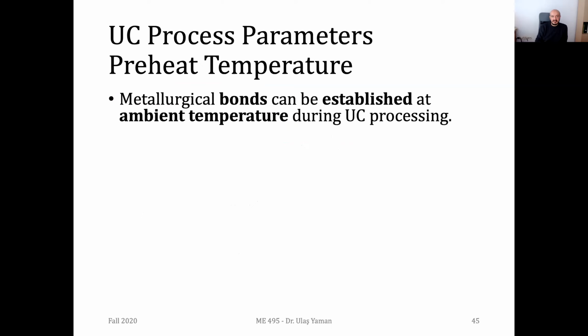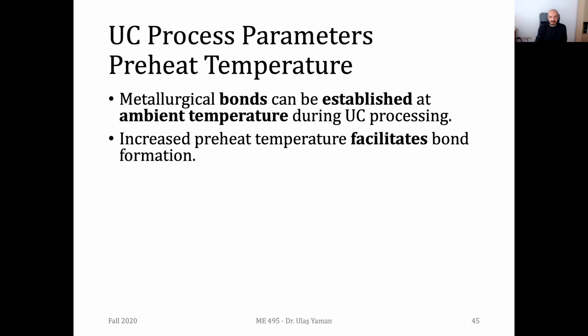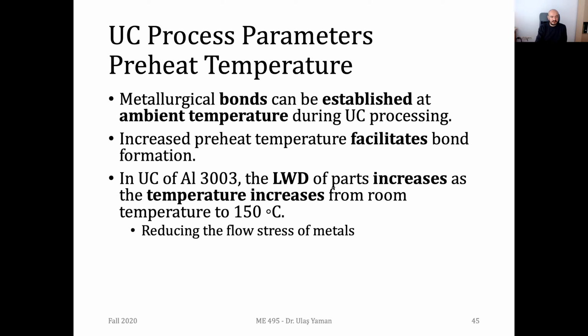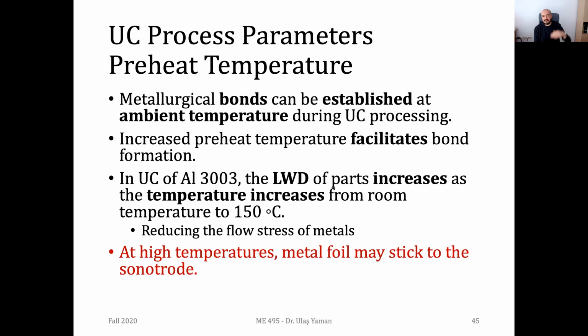Now we have preheat temperatures. If you have, let's say, a preheat temperature around 100 or 200 degrees, that may help you join the parts easily. This temperature depends on the material you are trying to join. If it's aluminum, you should keep it very low, but if it's steel, you may increase it to maybe 300 or 400 to make your joining easier. For aluminum, the preheat temperature is usually around 150 degrees. With its help, you can reduce the flow stress, which means that with low applied forces, you can start the plastic deformation.